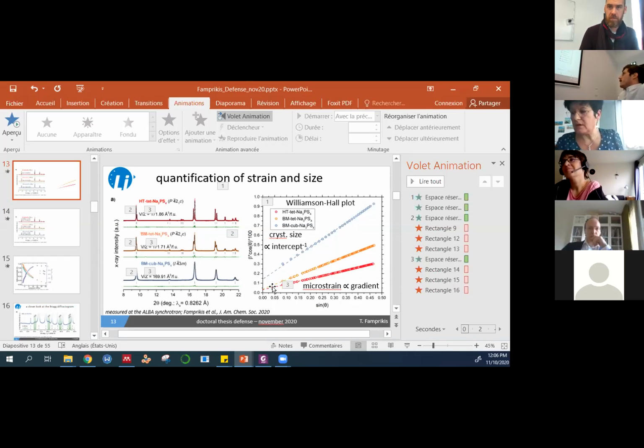The reason is that, as you mentioned, this microstructural effect could have an effect on the way you can densify your powders and so on, as you mentioned also afterwards. It is to really discriminate between different size and strain effects according to the crystallographic planes. And so theoretically you have different line broadening or asymmetry or things like that in your pattern.